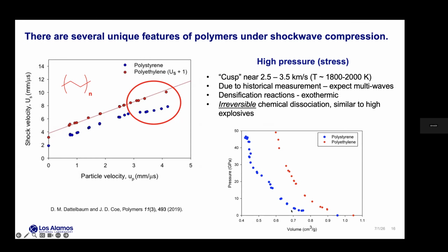And when you look at that in the pressure volume plane, it's a densification transition. And usually it occurs around 20 GPa. And we expect that above that transition, we would form products much like you have in high explosives, so solid carbon and different fluid mixtures based on the polymer structure. So that could include water, ammonia, things like that, methane.